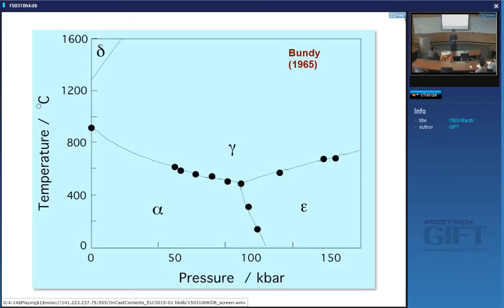Everyone assumes it's cubic, right? When you do your X-ray analysis or EBSD, you set the lattice parameter of ferrite to be a constant value, irrespective of A1, A2, A3, and you assume it's cubic. Now, the amount of tetragonality is actually very small. It's of the order of 10 to the minus 5. The difference between the two axes is very small, but it's not cubic. It's only above 760 degrees centigrade that alpha iron becomes cubic, because the spins are aligned randomly. It's no longer ferromagnetic.